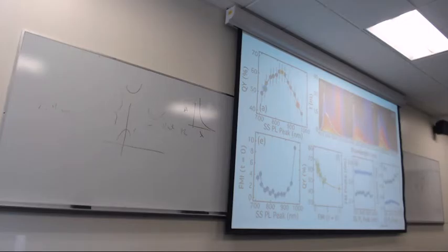The interesting thing about these materials is they've never been exposed to oxygen, so when we do gap versus size, we're the first paper that's ever seen excellent agreement with effective mass approximation. There's a PRB from 1995 by a couple of Japanese guys, the first ones to do this for silicon. I take the curve right out of their paper, put it on top of my data, and the agreement is almost uncanny. So that means EMA is a good approximation, but what does EMA say about this?